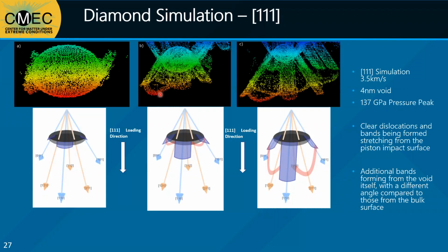This side view of the non-diamond atoms can hopefully help to illustrate what is going on. First, the void is compressed and nascent dislocations begin to form at the most concentrated stress areas. The rectangular bands begin forming, leaving stacking faults in their wake. The half loops are near the end of these rectangular bands, connecting them. As the bands grow in length and move farther away from each other in three-dimensional space, the half loops also continue to grow to keep connecting them without leaving behind their own stacking faults.